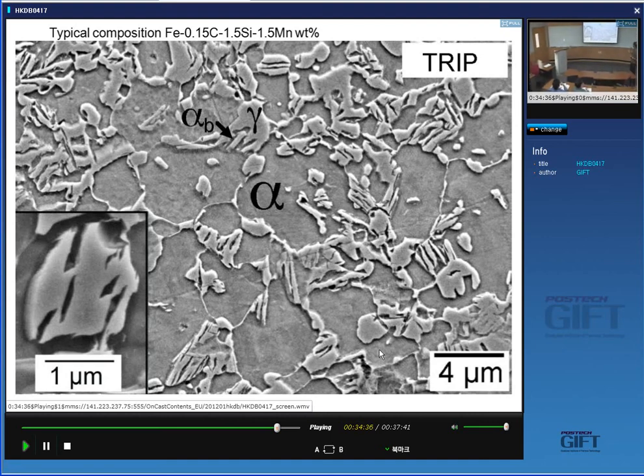Okay? So even though your steel has an average composition of only 0.15, you partition the carbon and the austenite is very rich in carbon, and that's what stabilizes it. Okay? So it's very, very clever, because you need a small amount of carbon if you want to weld the material, otherwise you get brittle martensite forming during spot welding. So the overall carbon concentration must be low, and it is, it's at 0.15, but you distribute the carbon heterogeneously inside your material by this very clever heat treatment, so that the austenite contains more than 1 weight percent carbon. Incredibly clever idea.